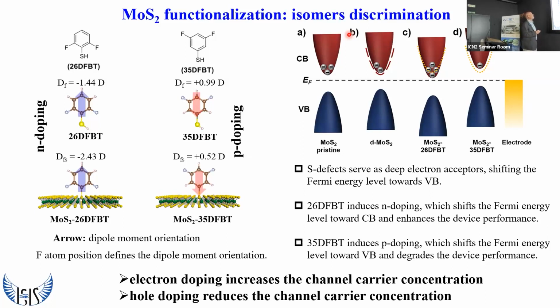So the idea here was to do a very basic study, taking a thiolated molecule, a benzene with 2 fluorine atoms that can be pointing either down or up. This means that the orientation of the dipole of the molecule can be controlled in such a way that when we use the 2,6-difluorobenzenethiol, we have a dipole that is pointing out of the surface, whereas when we use the 3,5, we have the dipole pointing towards the surface. In such a way that the 2,6 induces an n-doping effect, and the 3,5 induces a p-doping effect.